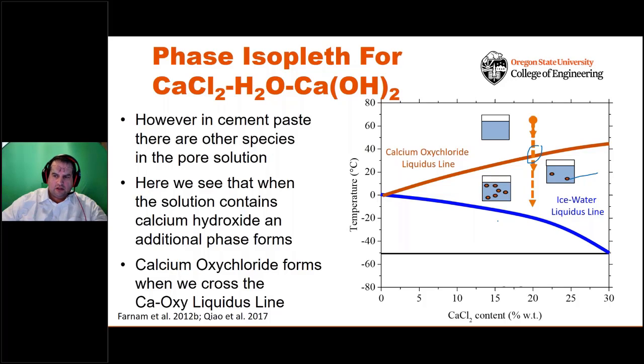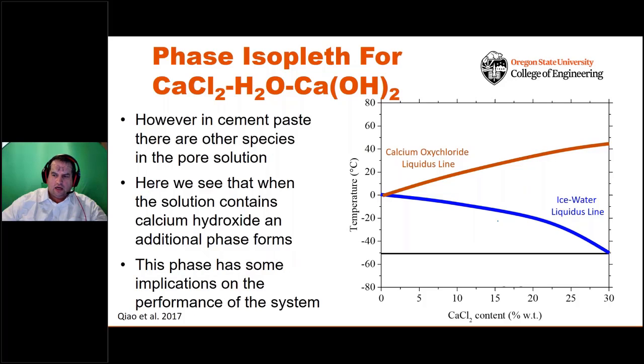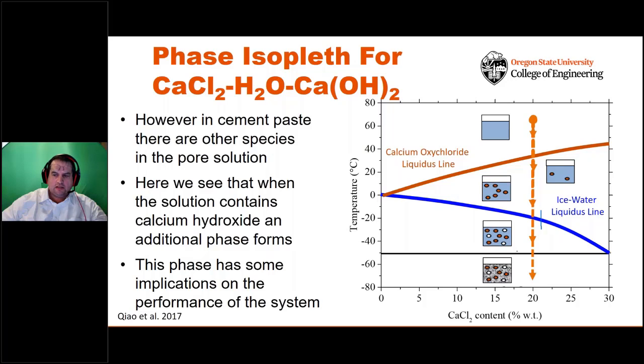That calcium oxychloride increases and increases until we get to a point where we now start to go across this blue line and we start to form ice. We go down to the minus 50 degrees, we get that eutectic solid. So there's some really big implications on this, because all of a sudden we're now forming this oxychloride, this expansive phase, which can be damaging our concrete.